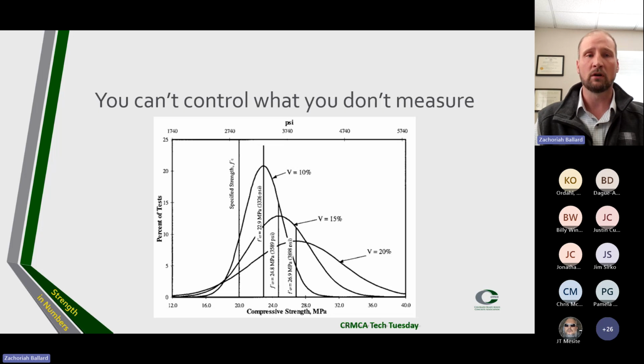And each one of these curves is still giving us the same failure rate of approximately 5 to maybe 10 percent, which we expect. We are going to get some low strength values. That's the way a normal distribution of results works. But if we're spending more time and money in quality control and mix design development, we can shift these curves to the left, reducing our over-design, which is going to reduce the costs on each of these mixes.